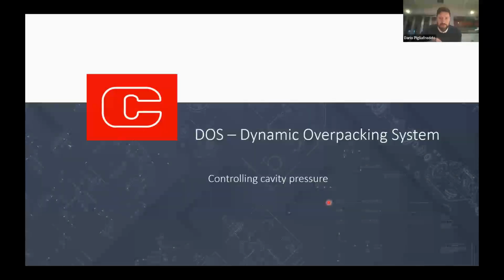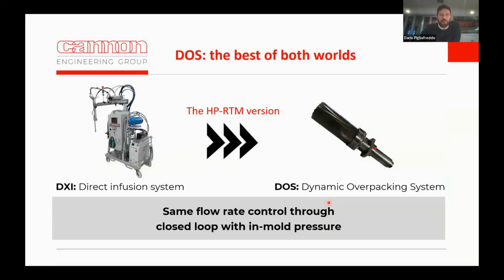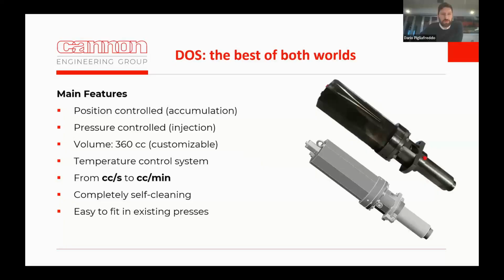Let's now discuss the second technology, which is quite interesting for aerospace applications, which is the DOS, or Dynamic Overpacking System, a device which is able to control cavity pressure. Transfer this concept to HPRTM. On the left, you see the direct infusion system. On the right, you see the Dynamic Overpacking System, which is basically an accumulation device able to re-emit mixed resin at a defined flow rate inside the cavity of our mold. The flow rate is defined by something that we set in terms of in-mold pressure, which now can be whatever we want, not just limited to 1 bar, but we can arrive, for example, to 100 bar, typical HPRTM pressures.